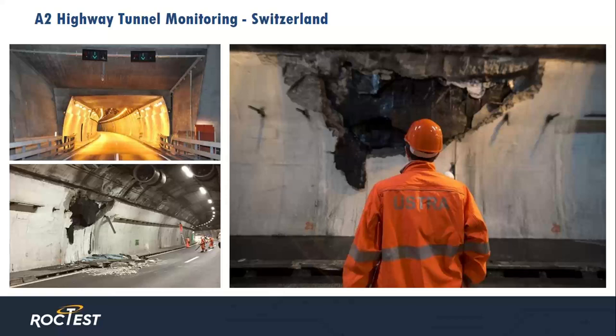Further investigation showed that the cause of the issue was meltwater percolating down through the rock mass and collecting behind the lining. So a decision was made to monitor both walls of the tunnel with a smart profile. It was monitoring tunnel wall deformation with the purpose of predicting future wall failure. In these failure zones, a remediation effort was put forth, and they installed some drains back behind there to dissipate the water, prevent it from collecting.